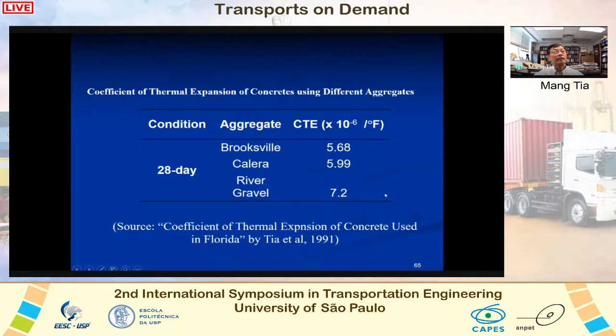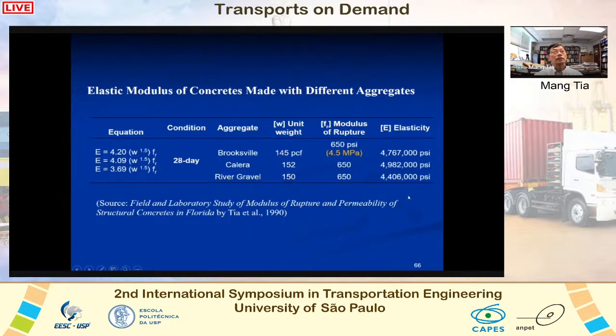It can be seen that the concrete made with the Brooksville limestone has the lowest coefficient of thermal expansion, and the one that used river gravel has the highest coefficient of thermal expansion. A flexural strength of concrete of 650 psi, which is equal to 4.5 megapascal, was used in the analysis.